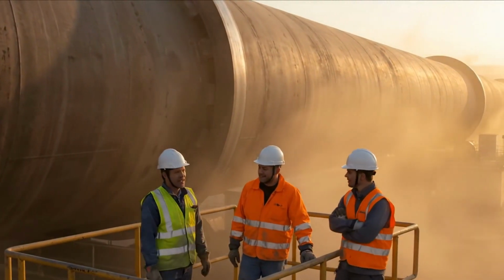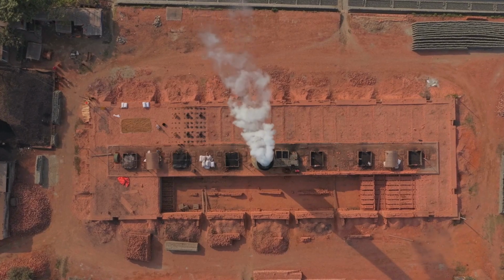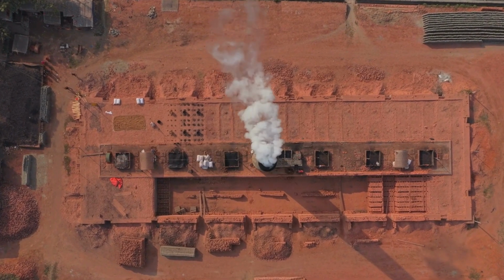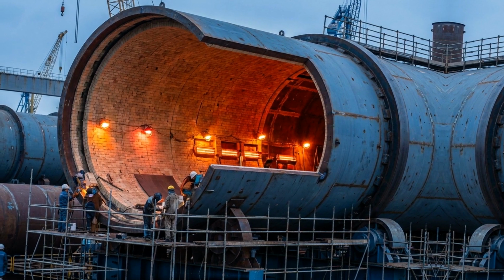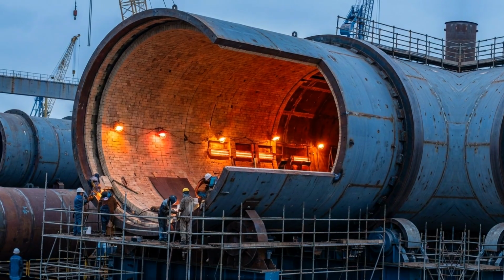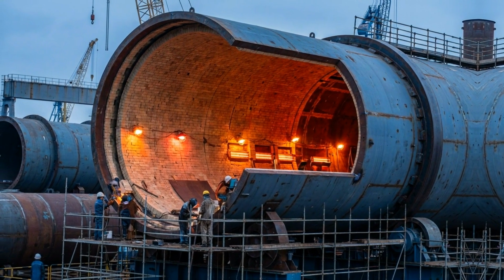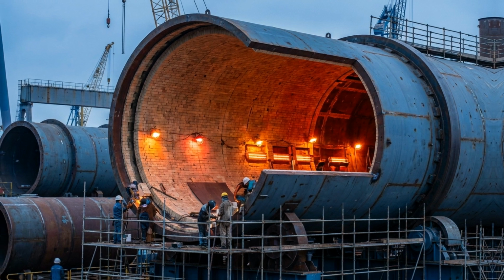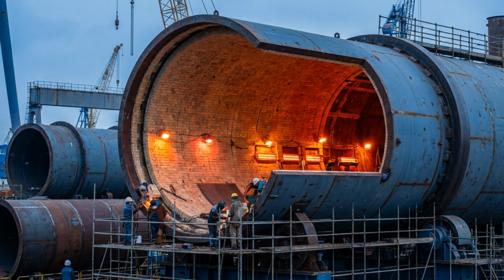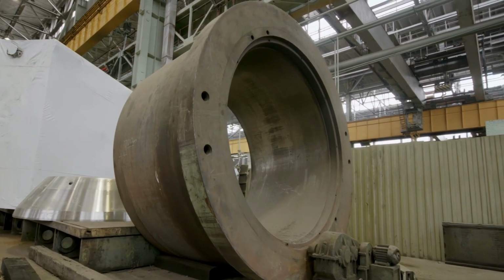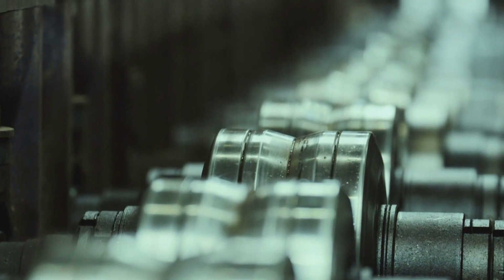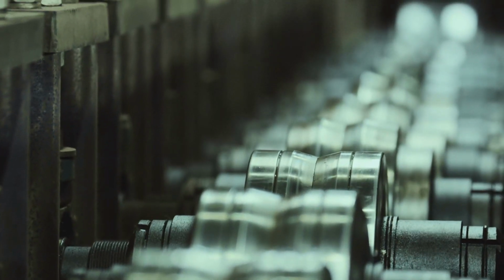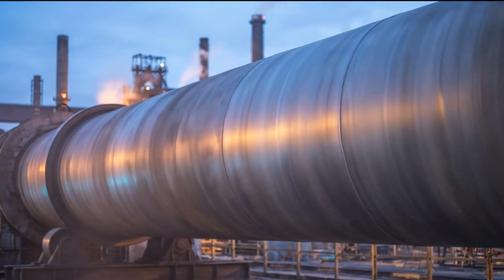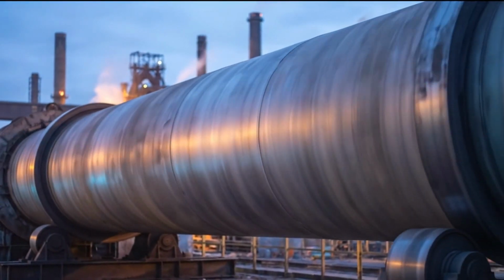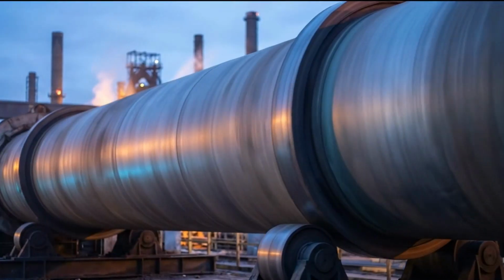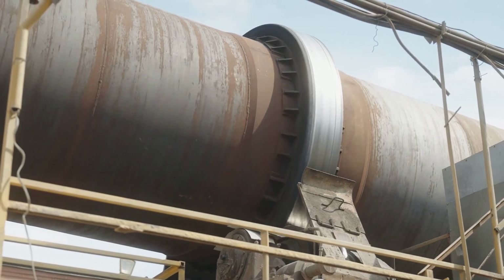The largest rotary kilns in operation are around 6 meters in internal diameter and up to 200 meters long. 200 meters, about 2/3 the height of the Eiffel Tower, laid on its side, rotating. The tube itself is made from rolled steel plate and lined internally with refractory brick, because the steel shell would fail immediately at the temperatures involved without it. The whole assembly sits on a series of large steel riding rings and support rollers, and it rotates at somewhere between 1 and 4 revolutions per minute. Slow, deliberate, continuous. The slight tilt is what moves the material through.